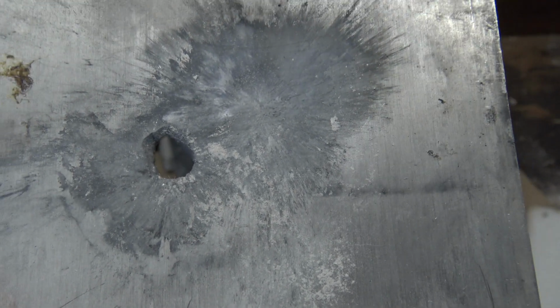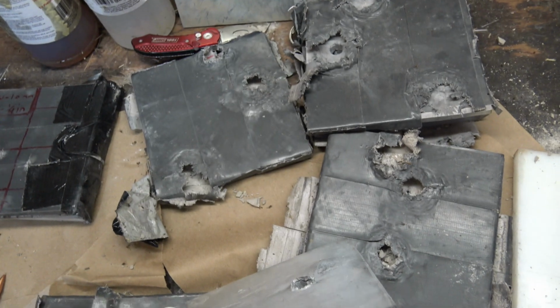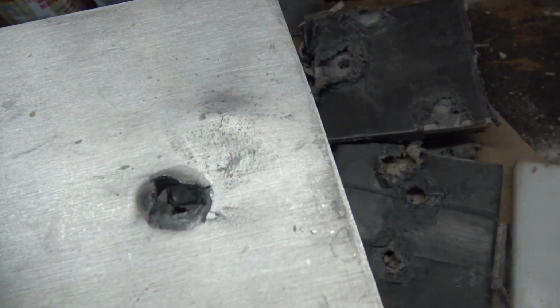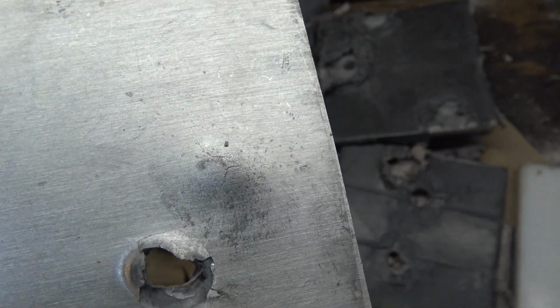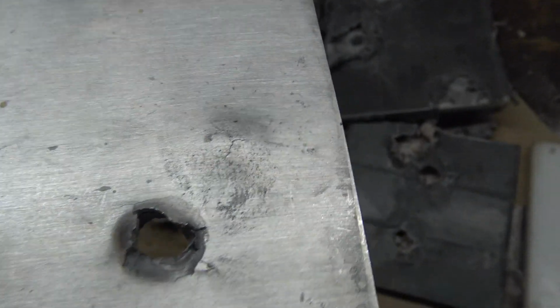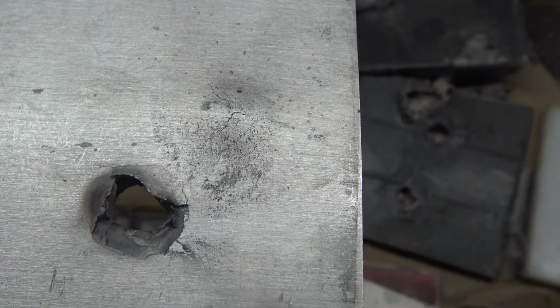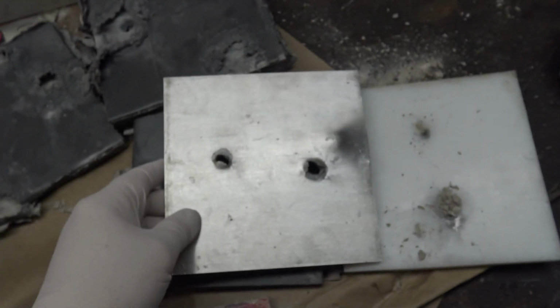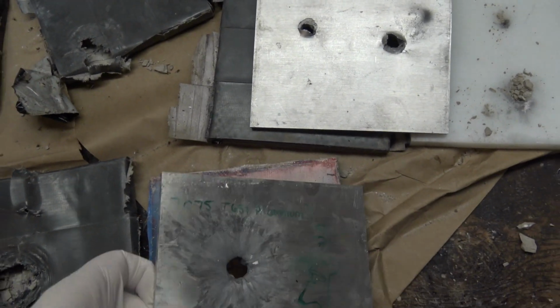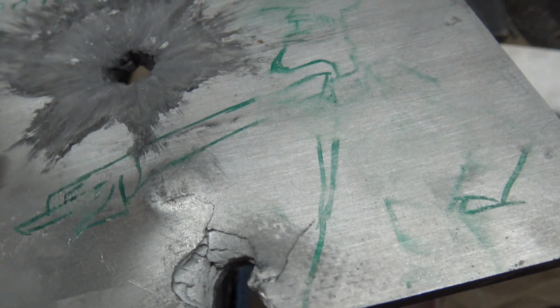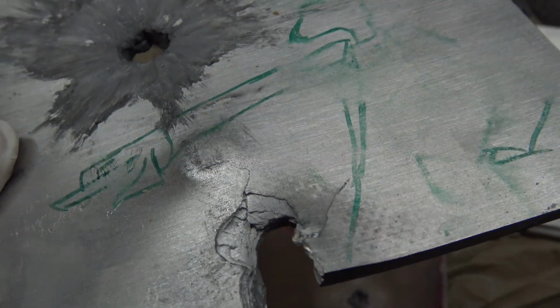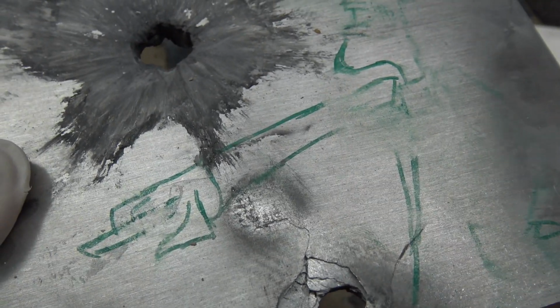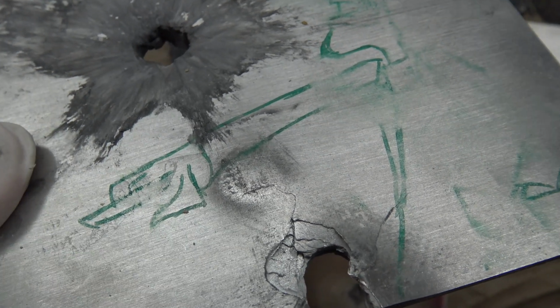Also, if a shot is placed close to the same area as a previous shot on the 7075, it will fail, with cracks forming from the previous shot's dimple to the new hole. Of course, the ceramic is also damaged in that area, but it just goes to show how brittle the T651 hardness is, and how it may be a big factor in its failure mode.